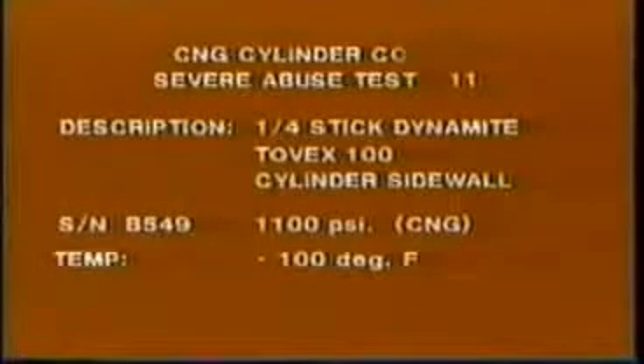But even though there was gas venting and a flash fire caused by a dynamite explosion, there was no ignition in the natural gas at any time. The cylinders contain the equivalent of approximately 5 3/4 gallons of gasoline, and a comparison should be drawn here to the amount of time it would take for a gasoline fire to be extinguished, whereas the natural gas simply vents safely into the atmosphere. Even if the natural gas had ignited, the only area that would have been affected would be on the periphery of the natural gas cloud. This is because 100% natural gas cannot burn.